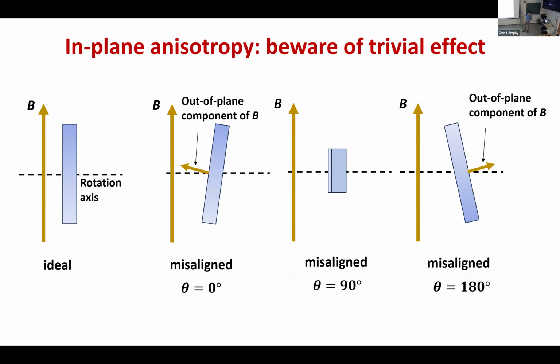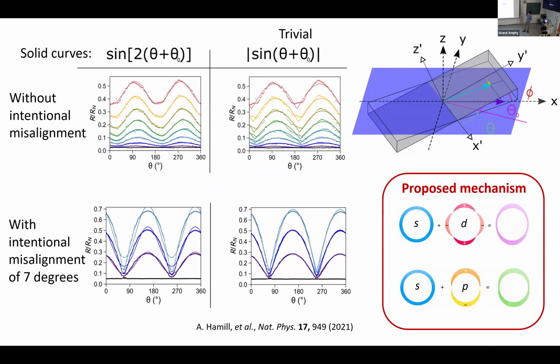So these 2 effects, if you think about it more quantitatively, both this one and the next one give you a sine theta dependence, because the out-of-plane component is just sine theta. But in this paper, what they observed is sine 2 theta. So they argue that this does not follow the expected trend from the trivial effect. They also demonstrate that if they intentionally tilt the sample with a misalignment of 7 degrees, then they can no longer see the sine 2 theta dependence. Now it becomes really the sine theta trivial effect. So from this, they argue this twofold symmetry is not really the trivial effects I just mentioned.